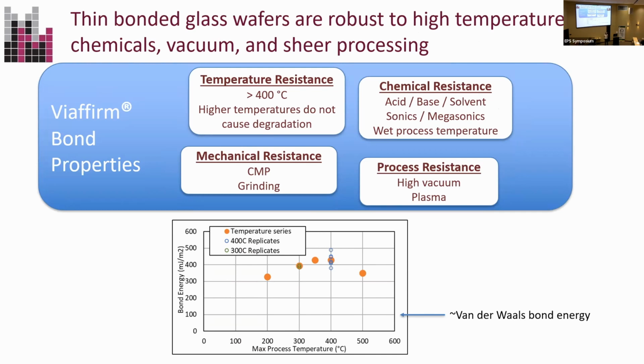If you compare that to a van der Waals bond, which is maybe on the order of about 100 millijoules per meter squared, this is strong enough to actually take you through whatever processing you want to do. So very temperature resistant. It's chemical resistant. You can throw it in acids, you can throw it in solvents, it doesn't matter. The wet processing is fine. I've mentioned the mechanical resistance, and we certainly do vacuum processing again and plasma processing.